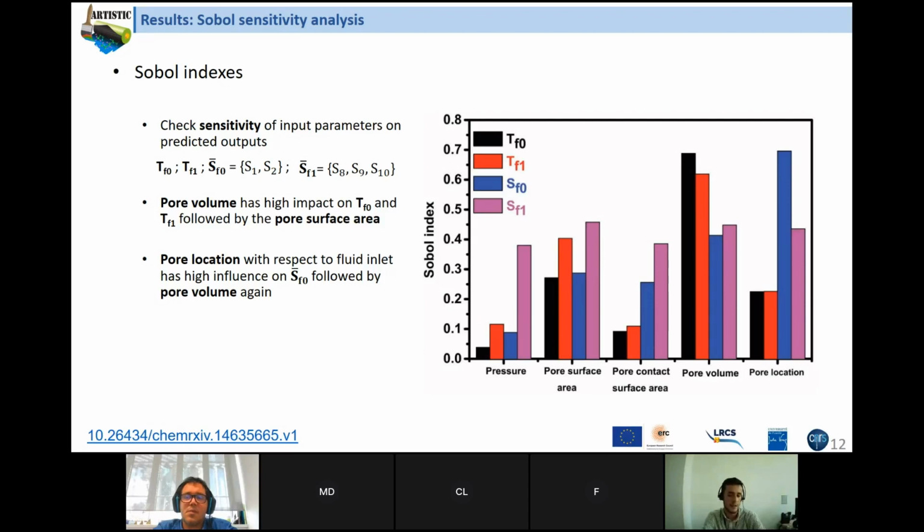is that fluid velocity slows down the deeper you go into the microstructure. So fluid velocity is not the same in the zones near the electrolyte inlet as when going deeper into the microstructure, right? So of course, pore location affects the initial values of the saturation onset, because depending on the fluid velocity, these saturation values will be steeper or not. So the saturation rate will grow faster or slower depending on the pore location.